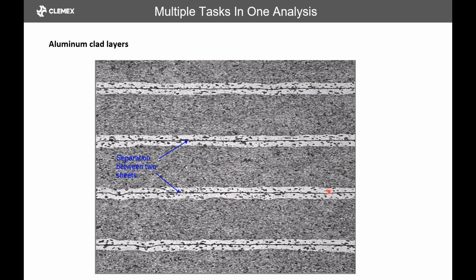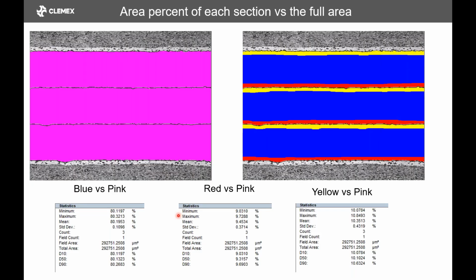This one here is an aluminum sample in which the white lines are clad. Basically, pure aluminum that is deposited or placed over the regular aluminum strip. The idea is that it would go into a radiator, and the clad is there to slow the corrosion. So what we need to do first is identify those middle lines. There's not just one sample, but all of those are separate lines. So again, with those edge finders, we can detect those. And here are our 3 layers that are complete.